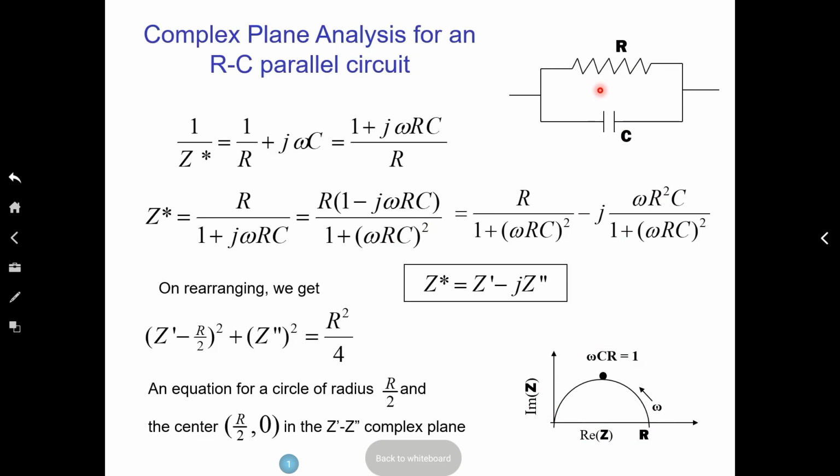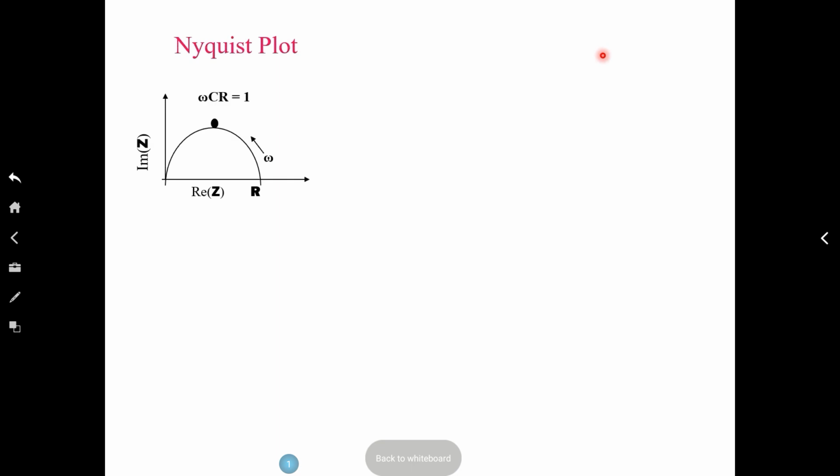And you see that these numbers will help you, because now you're going to associate this circuit analysis with material excitation. You're going to associate this R with something, and this C with something, etc. And the product of R and C will give you the relaxation kinetics. So if you know what the C value is and what the R value is, you can solve the problem. And then you'll see that, in fact, I have a slide here.